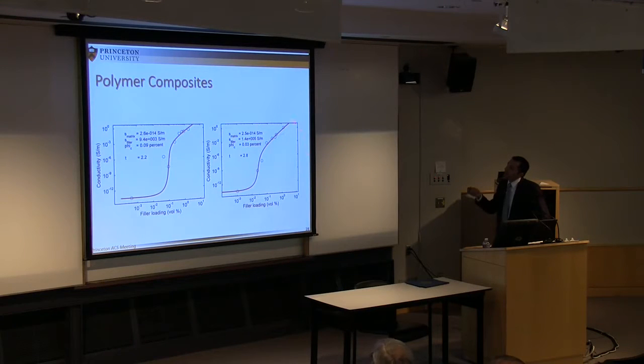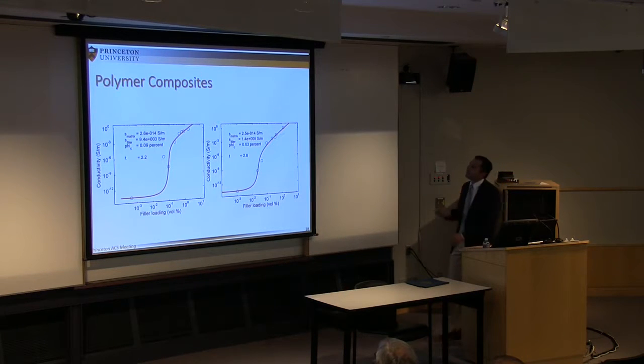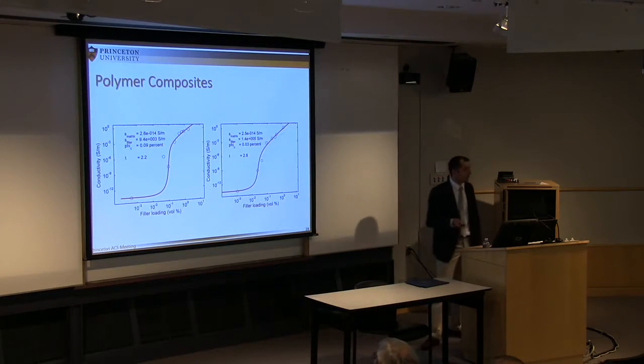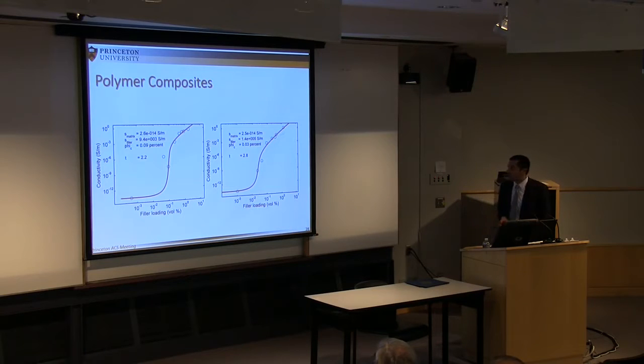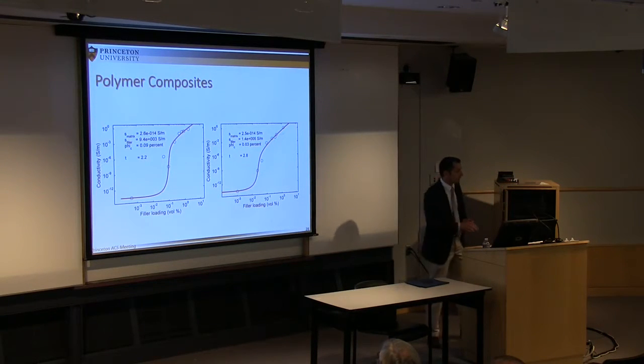And in the case of graphene now, you see that the percolation threshold is 3 times lower in this case. We have the percolation taking place at 0.03 versus 0.09 in the case of carbon black. So this is an interesting type of application of the graphene and carbon blacks for comparison. I forgot to mention it was in polydimethylsiloxane, so a soft silicone elastomer.